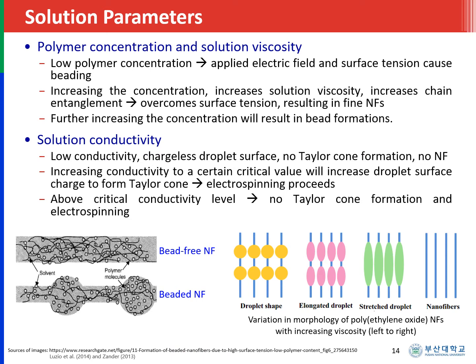The second group of electrospinning variables is solution parameters. Polymer concentration and solution viscosity are normally considered as one electrospinning variable because polymer concentration directly influences the viscosity of the solution. When the polymer concentration is low, the applied electric field and surface tension would cause beading of the nanofibers. If you increase the concentration, then the viscosity of the solution will increase and the polymer chain entanglement increases. This phenomenon will then overcome surface tension, resulting in fine nanofibers. However, further increasing the concentration will result in bead formations, and we don't want beaded nanofibers because they are actually poor quality nanofibers. The next one is solution conductivity.